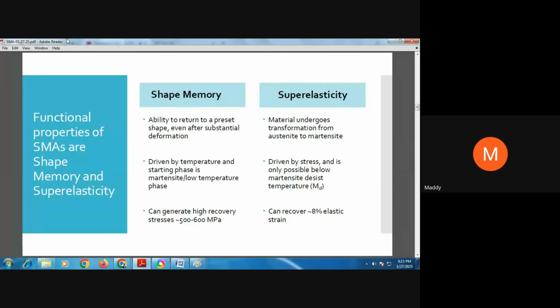We have been talking about the two functional properties, shape memory and superelasticity. So what are they and how are they induced? Shape memory is the ability of the material to return to a preset shape following substantial deformation. Shape memory is induced by temperature. You need to add heat or remove heat for this phase transformation to occur. And typically, you can go either from the high temperature austenite to the low temperature martensite, or vice versa. It's a reversible transformation. What's the advantage? This particular functional property is used in the actuator industry. You can see some examples down the slides. They are used as actuator springs, and you'll be amazed. You can see a lot of videos on YouTube or on the net where a tiny spring can lift some heavy load. Recovery stresses as high as 500 to 600 megapascals can be generated using this transformation.